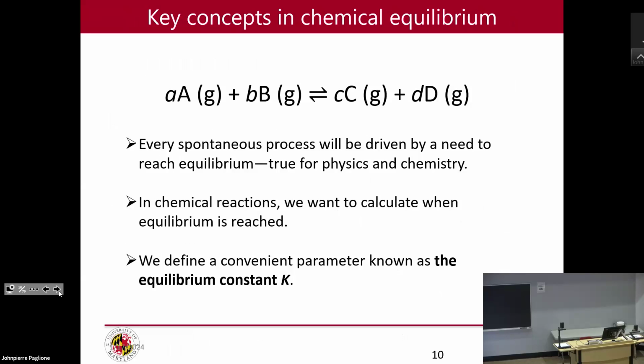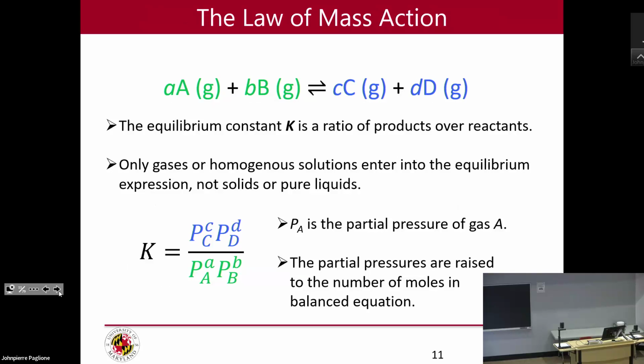And I'm going to say a little bit about chemical equilibrium, because this is sort of at the heart of what's going on with these. And that is that we have some kind of reaction going to a product. Our product here is our crystal, right? And the thing about equilibrium is that it's a dynamic process. And so the forward and the back reaction is always happening, in fact. And what you want to do is push equilibrium in one direction. And so that is called the law of mass action, where you have this equilibrium constant, it's just products over reactants. And when John Mitchell was talking about, for example, the equilibrium constant in the induction furnace under high oxygen pressure, you noted that the equilibrium constant was just the oxygen partial pressure, okay, or the fugacity of the oxygen.